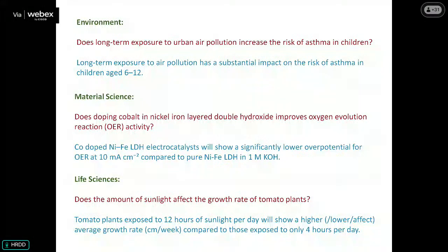A specific statement. Okay: cobalt-doped nickel iron layered double hydroxide will show a significantly lower overpotential for OER at 10 milliampere per centimeter square compared to pure nickel iron LDH in 1 molar KOH. So you have nickel iron layered double hydroxide, a layered structure, and those catalysts are active for the oxygen evolution reaction itself. Doping cobalt means instead of nickel or instead of iron, I substitute some amount of nickel or some amount of iron and put cobalt.